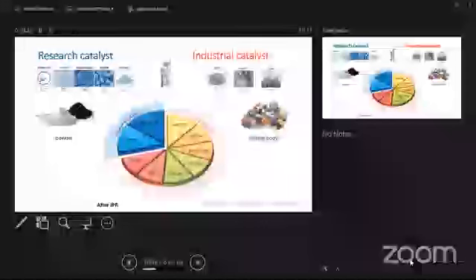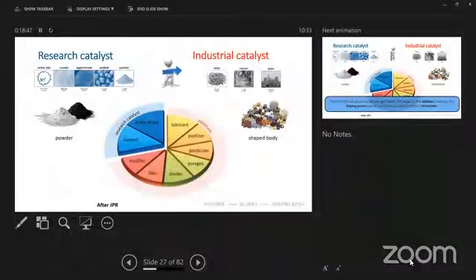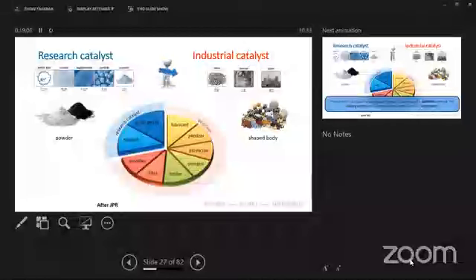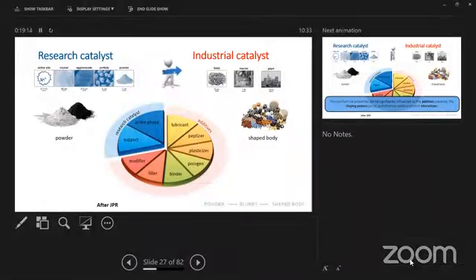In reality, you have the binder, maybe a clay. And this clay might have its own catalytic properties. And the amount of the binder can be 30–40%. So imagine you tailor-made your catalyst, which can be, for example, a zeolite or a metal supported on zeolite. You optimize it for a certain reaction. And then when you go to industry, you should make an extrudate, and then you use, for example, I don't know, aluminum